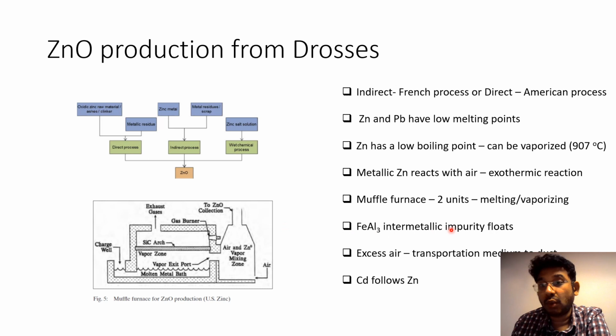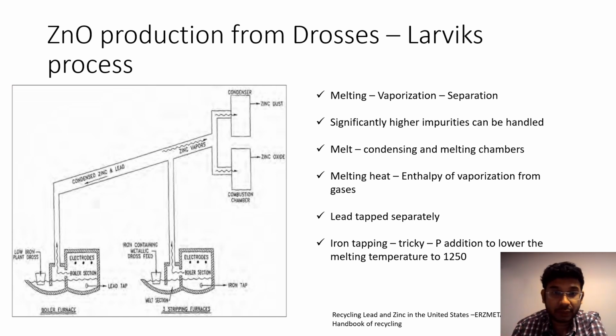Then let's go to another type of furnace. Essentially, the chemistry is really the same, except the furnace construction is a bit different. In the Larvik furnace, what you have essentially is three different zones: the melting, vaporization, and separation zones. The difference between the muffle furnace and the Larvik furnace is this: different types of impurities can be handled in a Larvik furnace and not in a muffle furnace. How do they achieve this feat? By simply having two different taps, a lead tap and an iron tap. So what do they do? It's essentially quite simple.